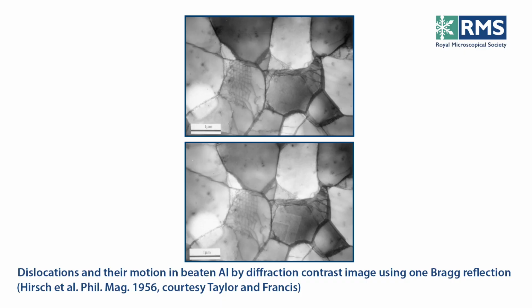Anyway, Bob Horn, who had a biological background and was more interested in microscopy, he wasn't interested in diffraction, set the thing up for the optimum microscopy setup, which involved the operation of the double condenser lens. And when we turned up, he'd set the thing up like this, and then when he opened up the condenser aperture, lo and behold, all those lines and spots started moving all over the place, and it became perfectly obvious that they were dislocations. We were very lucky in that something most unexpected happened.